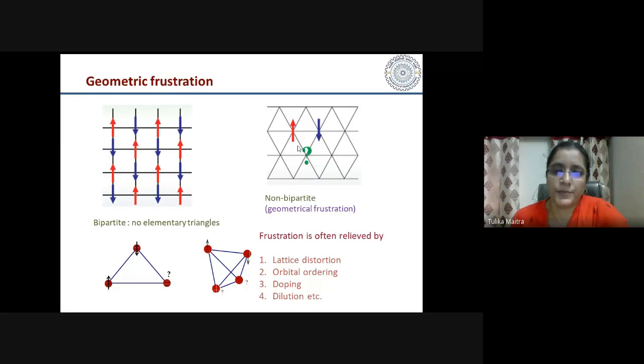If I put the up spin here, then this bond will be ferromagnetic, so it will remain frustrated. If I put a down spin here, then this bond will be ferromagnetic and hence will remain frustrated. This kind of frustration is called geometric frustration due to the lattice, and this gives rise to a large degeneracy in the ground state. This frustration can often be relieved by lattice distortion or orbital ordering or doping, etc.